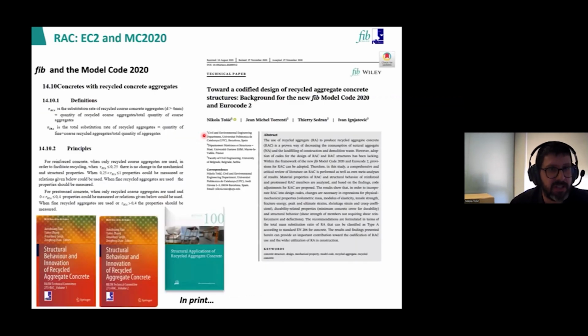Something very similar is in the Model Code, only there we were not bound by EN 206 and other standards. So actually, everything is still defined in a coefficient of total substitution ratio, tau TRA, total recycled aggregate, but actually the limitations are in terms of coarse recycled aggregate. And here we allow up to 100% of coarse aggregate substitution, but if you go into the text, you will see that the expressions are exactly the same. The background is in this article, in the Eurocode 2 background.